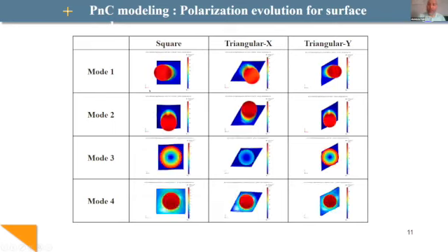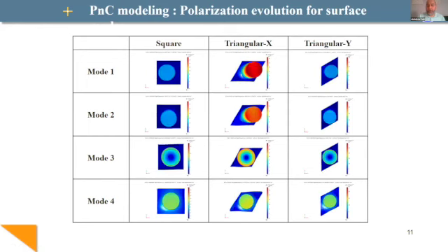And we can see this, for example, just for mode 1 and mode 2. For the square, we have the two bending modes, along the X direction and along the Y direction. And for triangular X, we have some elliptic polarization of the bending mode. And for triangular Y, we have exactly the same polarization of the pillar as the square mode. And we can see it for the other modes.